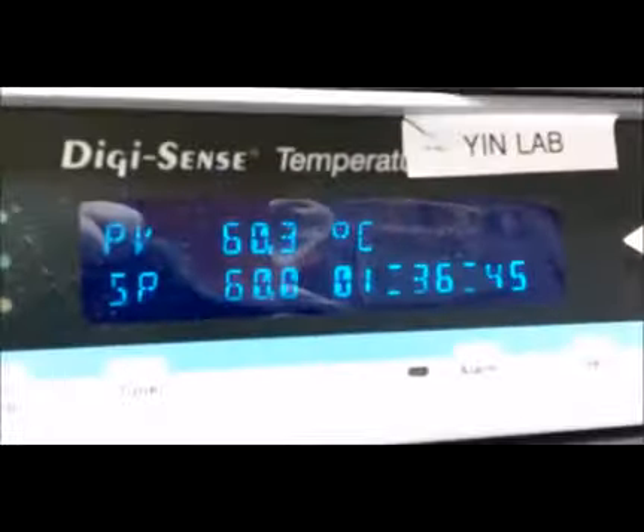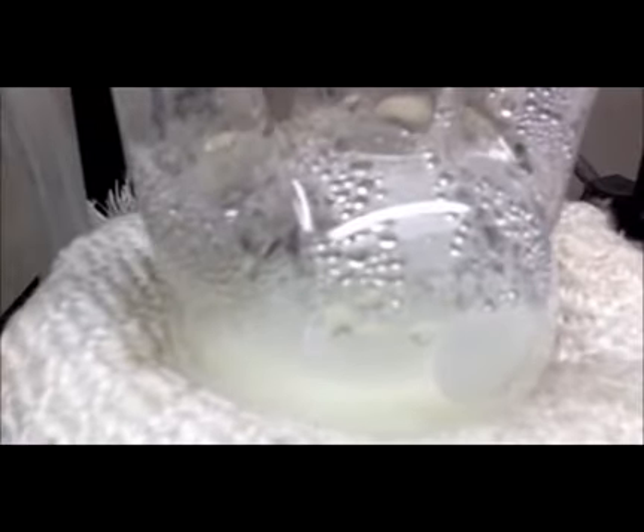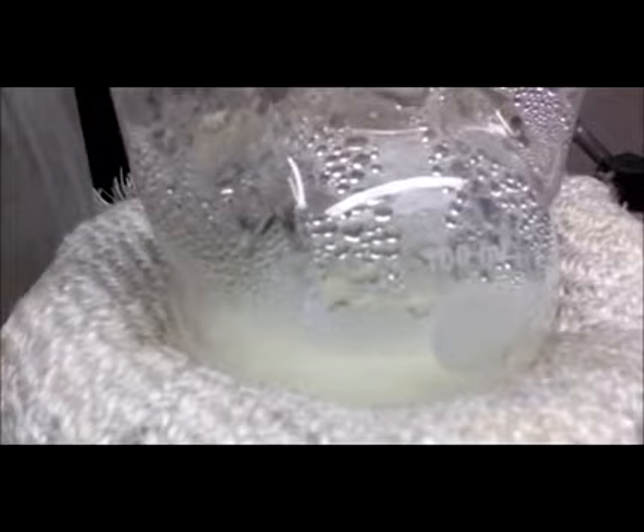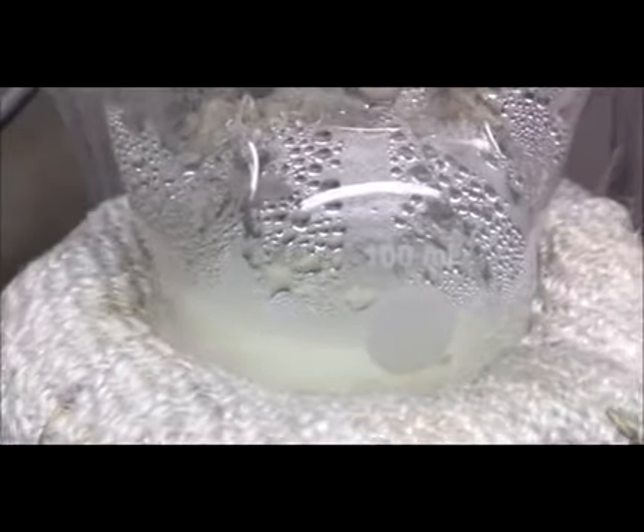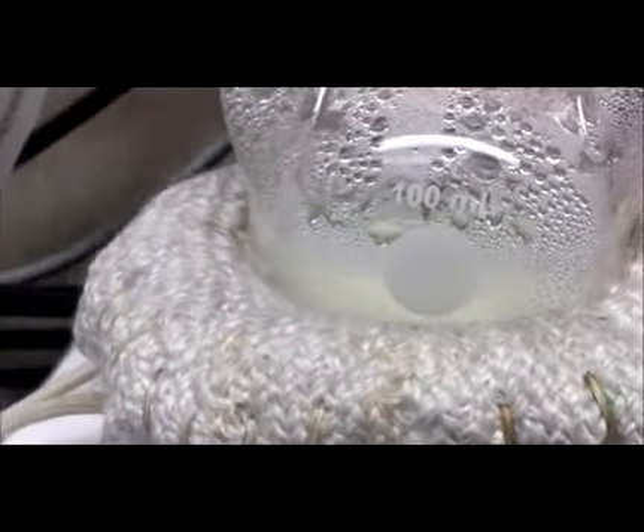Once the temperature has reached 60 degrees Celsius, we then add 70 microliters of formaldehyde and add 0.5 milliliters of the resorcinol. As you can see, when we add the resorcinol, we can see a slight color change from white to a pale yellow. We then heat it at 60 degrees Celsius for an hour and 45 minutes.